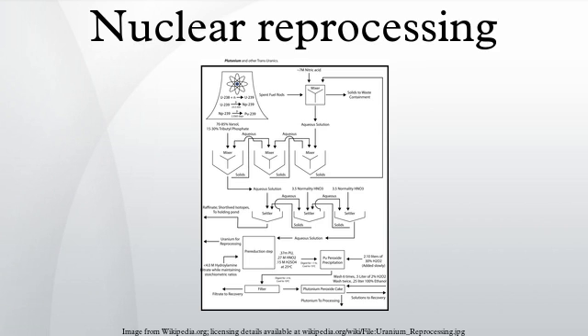Distillation of the residue at higher temperatures can separate lower boiling transition metal fluorides and alkali metal fluorides from higher boiling lanthanide, alkaline earth metal and yttrium fluorides. The temperatures involved are much higher, but can be lowered somewhat by distilling in a vacuum. If a carrier salt like lithium fluoride or sodium fluoride is being used as a solvent, high-temperature distillation is a way to separate the carrier salt for reuse. Molten salt reactor designs carry out fluoride volatility reprocessing continuously or at frequent intervals.